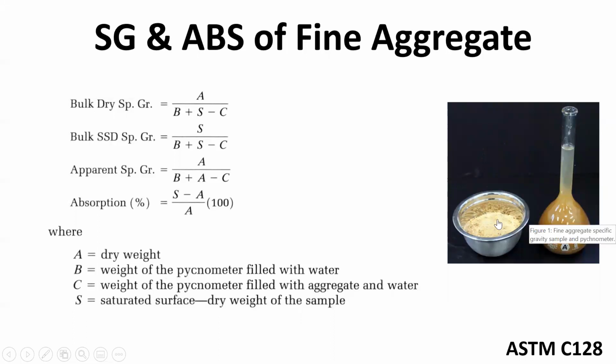But in essence, you fill up your flask full of water. You make sure your fine aggregate has free water in it, so it's well above SSD, if you're trying to measure for SSD. A lot of times you'll take a blow dryer or a fan and continuously mix the sample and let it dry out until that sample finally doesn't mold, isn't able to stick together.